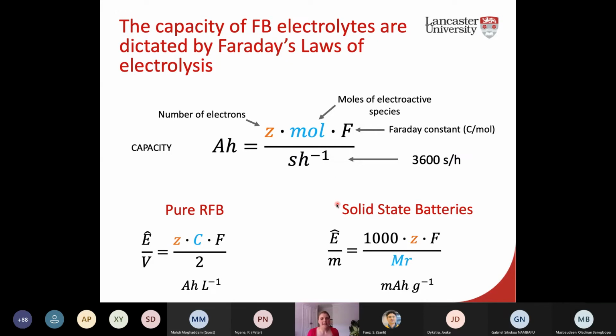And this is for the capacity in the first instance here. Essentially, the capacity of your battery depends on the number of electrons involved in your charge-discharge process, and the moles of electroactive species that you have. Then you multiply by Faraday's constant and the time constant, which is 3,600 seconds per hour, to give you that amp hour unit. And that gives you a quantity of how much energy you have in an hour of having your material.